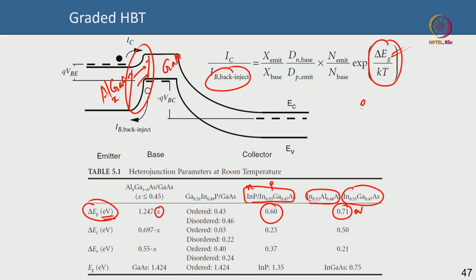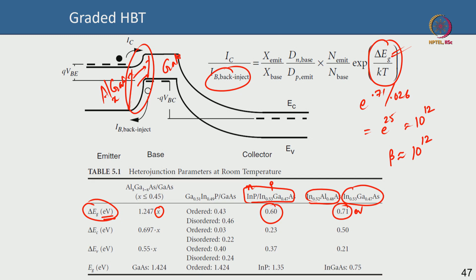Indium aluminum arsenide with indium gallium arsenide of the appropriate composition gives you 0.71 electron volt of band discontinuity — it is incredible. E to the power (0.71 / 0.026) is around e to the power 25 or 30, and since e to the power 2.3 is close to 10, this is like 10 to the power 12. It means your beta can theoretically be 10 to the power 12 — an insanely large number. In reality of course you would not get that, but you will still get a very, very large beta.